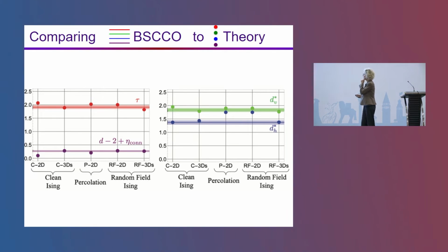So let me walk you through what these charts are. The horizontal lines are the exponents that we extracted from the data set on BSCCO. And then the width of that line is the error bar. Okay? And then the circles are theoretical calculations of those exponents. And so here we have the Fisher exponent, which is about the cluster size distribution. Here we have the paraconductivity correlation function exponent, the one I said is also power law at Ising models. We have the volume fractal dimension here and the Hall fractal dimension here. And then we figure out which ones are closest to the experiment.